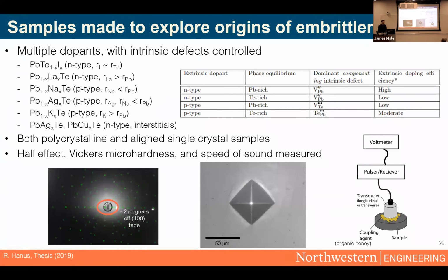And in the majority of those samples at least, I tried to control phase equilibrium. So I used methods like saturation annealing to exert some sort of control over my intrinsic defects and also my doping efficiency. I also did both single crystal and polycrystalline samples to see if grain boundaries were the main reason for this disparity. And in all my samples, I measured the Hall effect, which gives me doping levels and carrier concentrations. I measured the hardness, and I also measured the speed of sound.